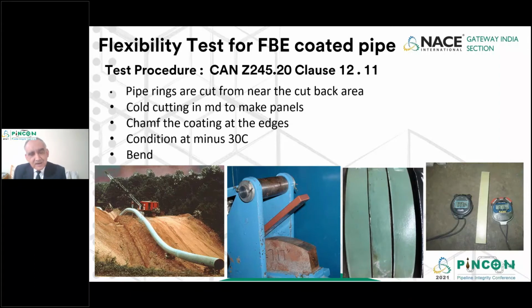The panel is taken out, and a stopwatch is there to measure how much time it takes to bend. So there's a guideline on how quickly it has to be bent. The panel is placed in the bending machine against a mandrel, and the mandrel is designed for an angle of something like 3 degrees per pipe diameter. And the bending is done very quickly. The details of speed and time are written in the specification.